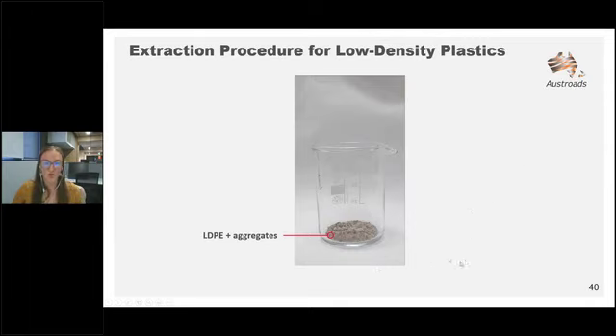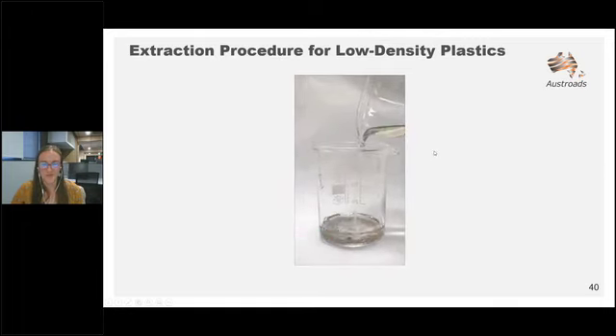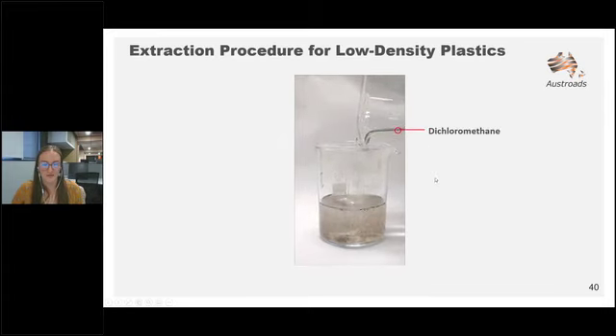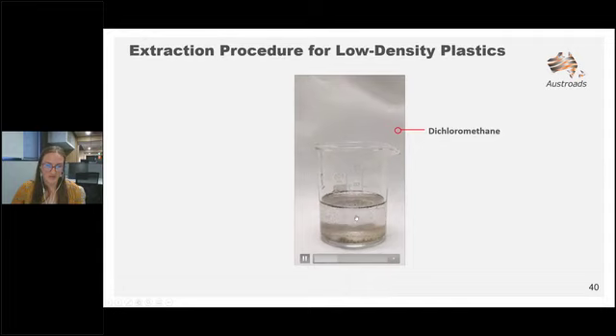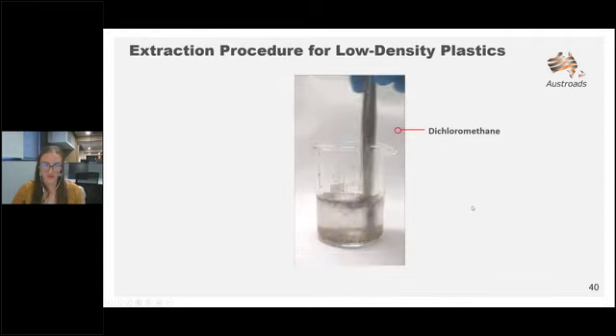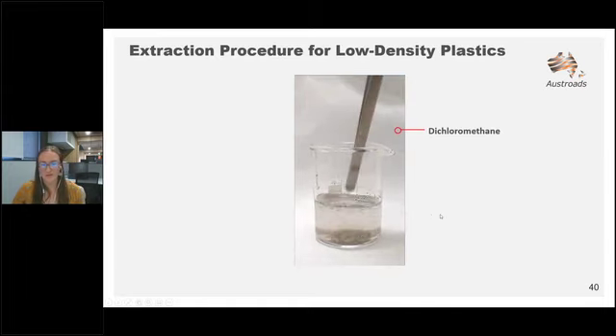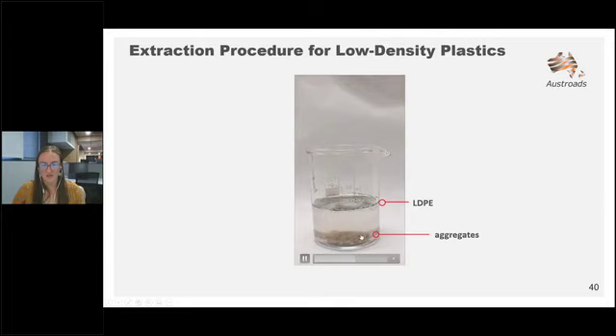So this is not what I used to extract the microplastics from the residues, but this is an example to show you the technique. So I made here just for you a mixture of LDPE and aggregates, and I then added the organic solvent that I used for density separation. So in that case, dichloromethane. And what you can see is that the black particles start floating straight away. And the black particles are actually polyethylene particles. So what you end up with at the end is aggregates settling at the bottom of the beaker and polyethylene floating at the top of the beaker. So this is the principle that I use to extract the microplastics from the residues.